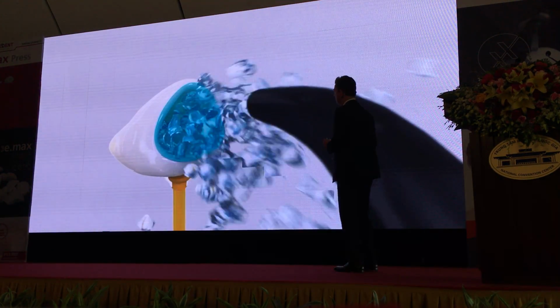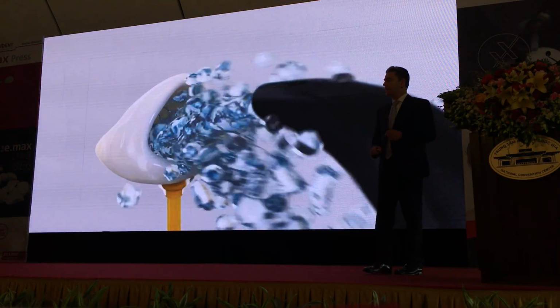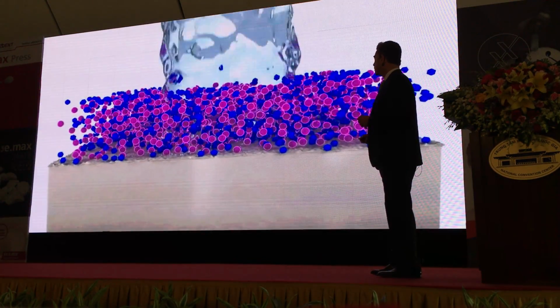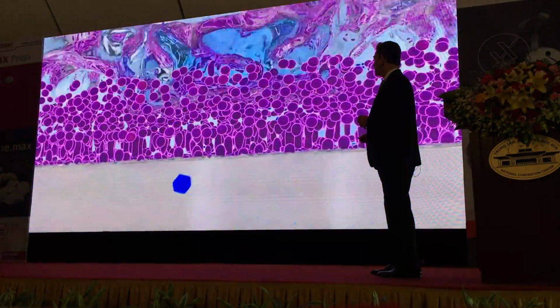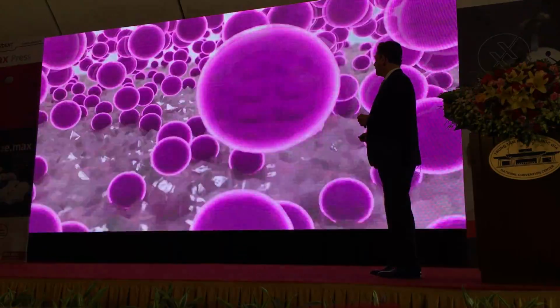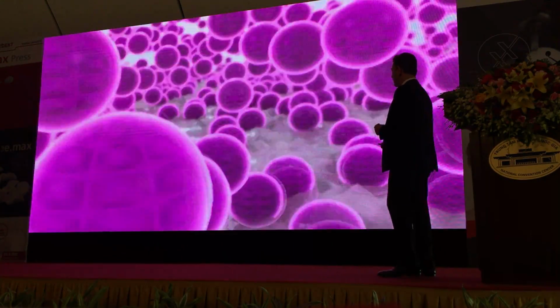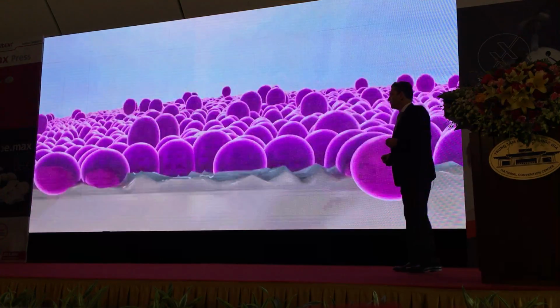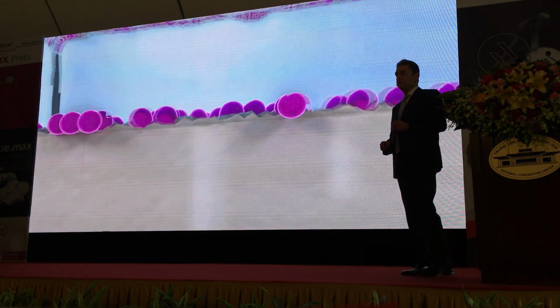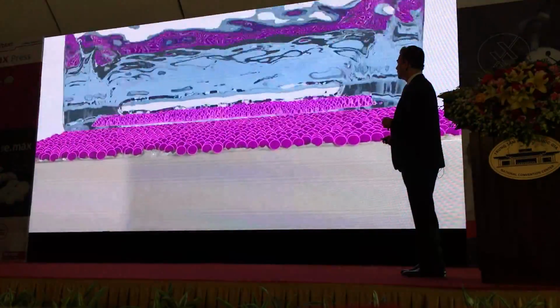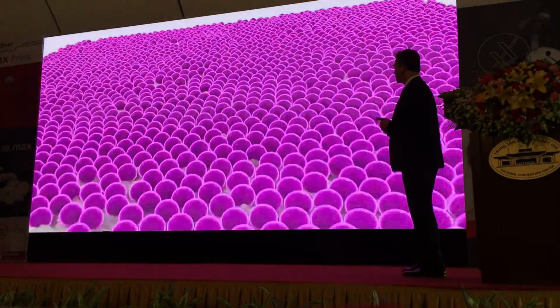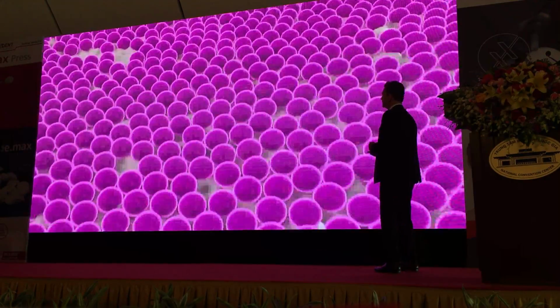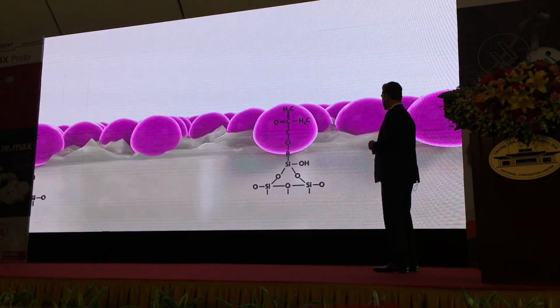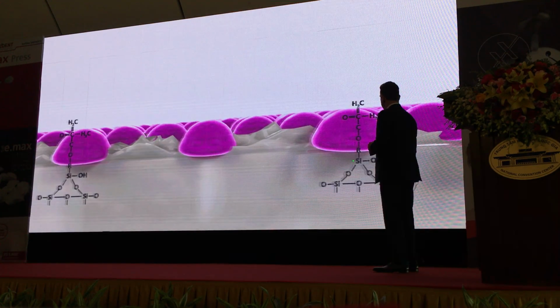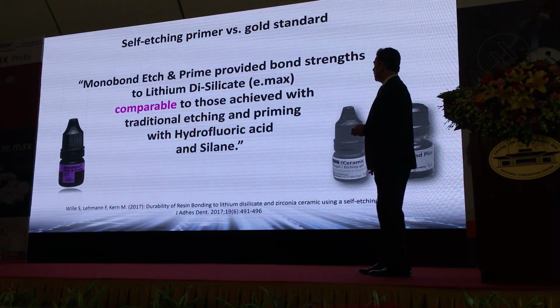Now after a waiting time of another 40 seconds, we can rinse it off and we dry this. You can see that's the water to rinse off the hydrofluoric acid. And we can then dry it. And what you see now is the silane. So the silane is now creating the chemical bond to that surface. So that's a clean, etched, and silanized surface. You can see this is the connection, the chemical bond of the silane methacrylate with the ceramic surface. And this is how it works.